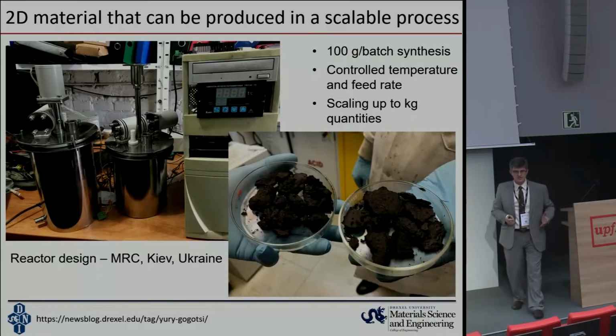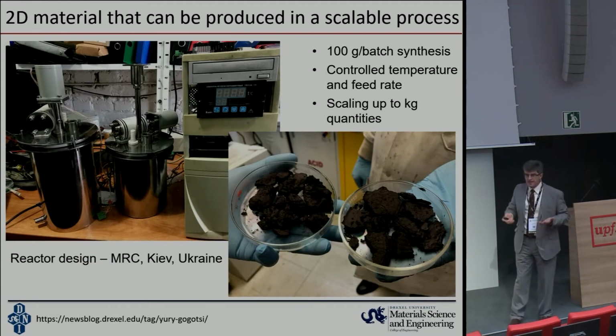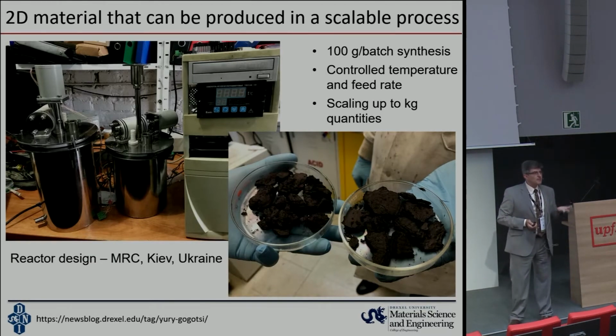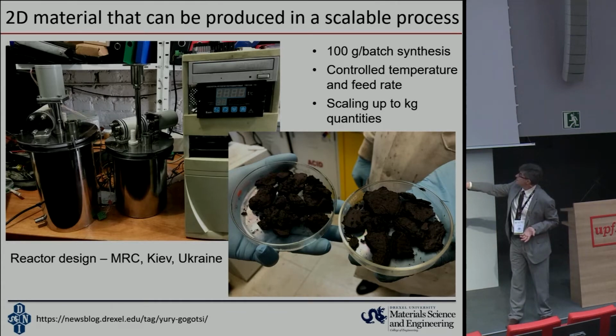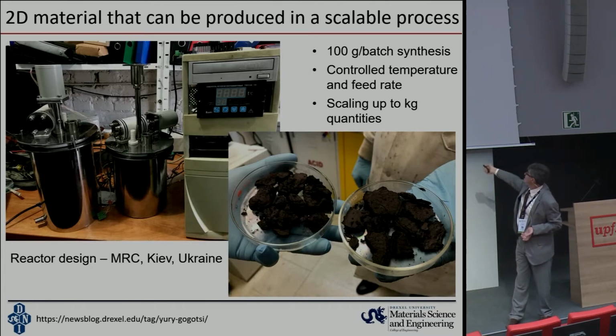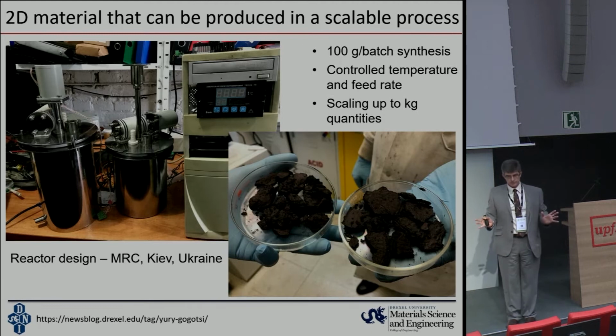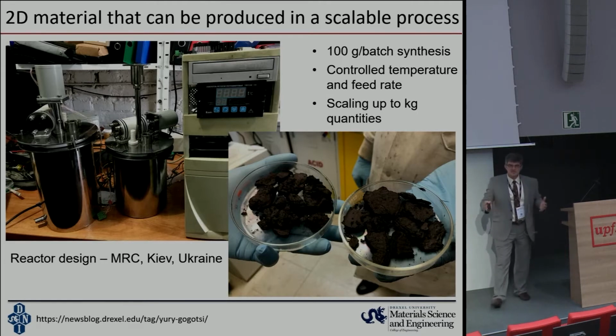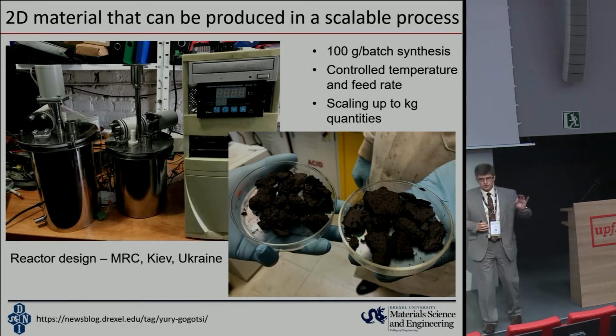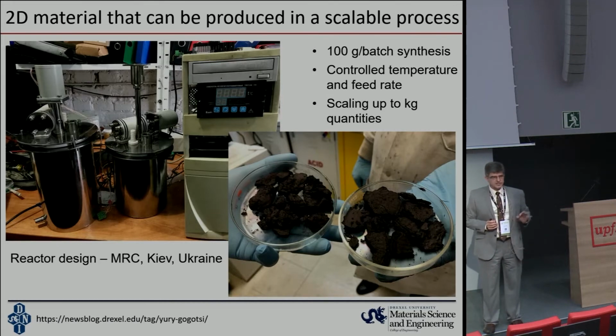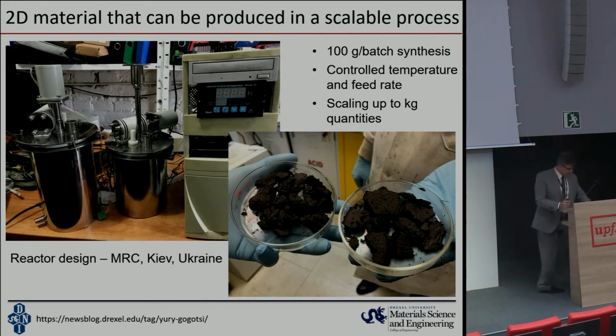What is important in this case? We can make this material already now in 100 or even 200 gram batches in the lab here. So these are reactors developed for us by Materials Research Center in Ukraine here. And this is like a, not chocolate, this is titanium carbide Ti3C2 MXene coming from a single synthesis batch here. And of course, there are billions of two-dimensional flakes that you can produce by dissolving in water here. And this makes a big difference. What it means is that here, we can use this material not only for single flake electronic devices, small applications here. They can be produced in quantities sufficient for using in batteries, supercapacitors, to produce coatings for a variety of applications.